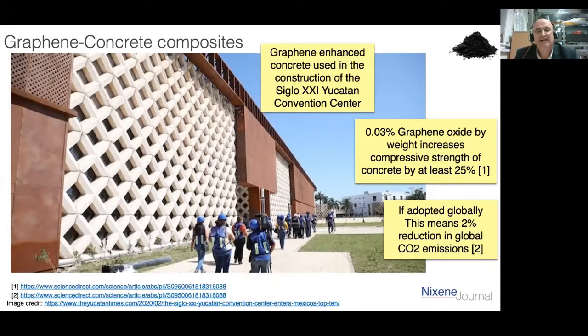And we'll mention this later. If you adopt that, it means a 2% reduction in global CO2 emissions, which is just incredible. Again, low-hanging fruit, and I get really frustrated that this isn't adopted and taken forward. One of the challenges with adoption is that concrete companies are going to be selling 20% less of their products. So we need to get governments involved, with a level of intervention to offset that potential loss, and also certification of this material so it can be adopted right across the trade. You just think how much concrete is used globally. So a minimum of 2% saving on global emissions almost immediately.